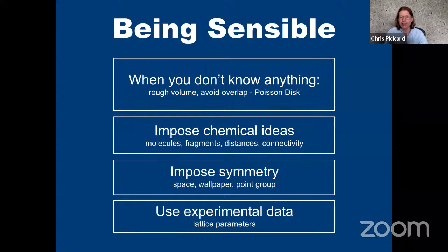If you know more about the system, then it's a good idea to use those chemical ideas. Those might be just fundamental chemical ideas, such as the existence of molecules or fragments in a complex structure. The fact that atoms have certain preferred distances that they want to be from each other, these can all be imposed in your initial random structures, or even the connectivity. So if you're looking for tetrahedrally bonded carbon, then you could make a random structure, but only quantum mechanically relax those structures that are tetrahedrally bonded.